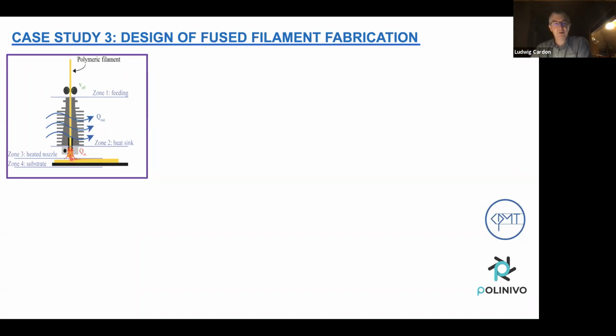So what we do in our research, we divide this kind of printer systems, extrusion-based micro extrusion systems, in 4 zones. So zone number 1 is what we call our feeding, where the filament is still in solid phase. Zone number 2 is the heat sink in between the free filament and the guidance. This one is cooled down. And then we have zone 3 and 4, which is the nozzle itself, and finally the deposition on the substrate and the cooling down. So you somewhat can see here that we cool down, so the hot goes from red to yellow, to indicate the cooling down process of the system.